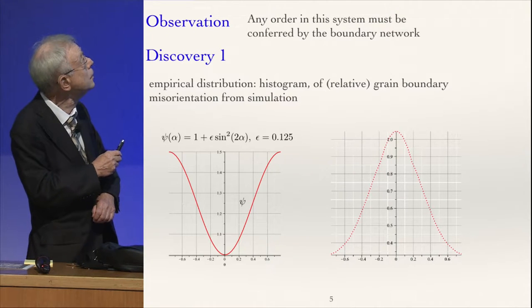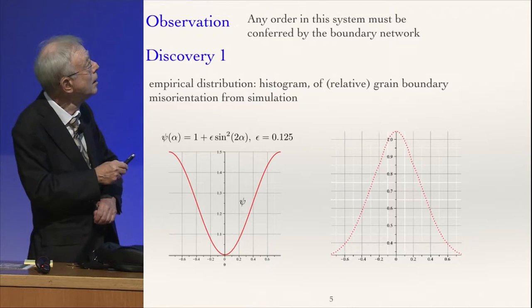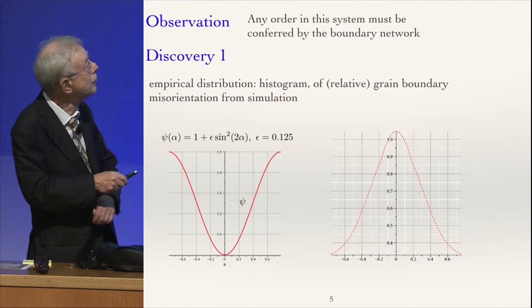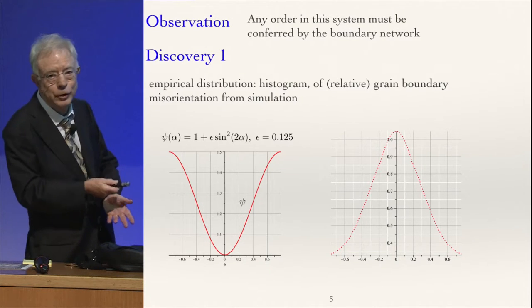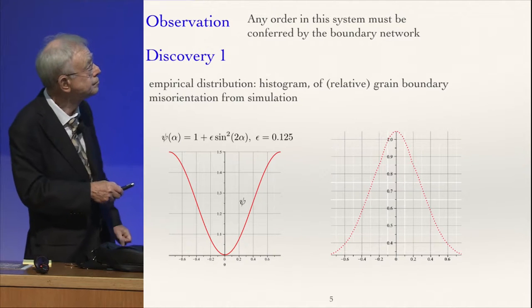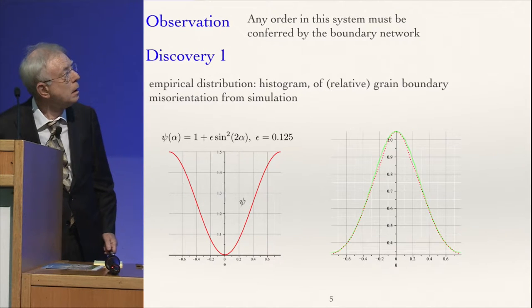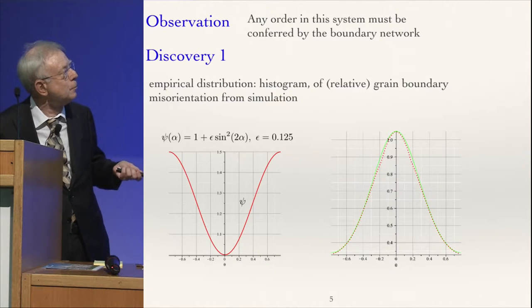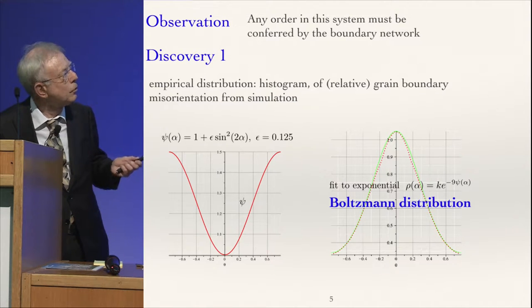Here we were able to make a simulation. So this is the empirical distribution, or the histogram, of relative grain boundary misorientations from a simulation with this energy, which is essentially x squared. It has to be periodic, of course. And here is the green curve, which you can barely make out. I tried not to use much green later on. It is a plot fitting it to a smooth curve, and that smooth curve turns out to be a Boltzmann distribution for the energy with which we simulated.